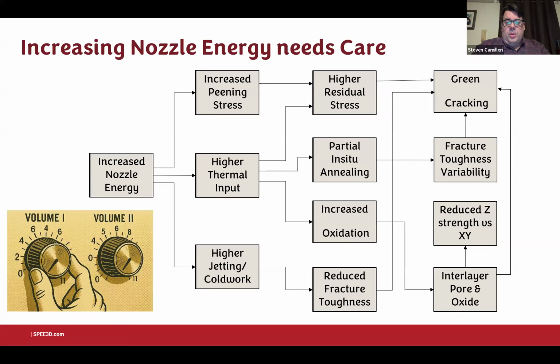Okay, that's level one. What does the increased peening stress actually do though? Well, it's generating residual stress, which may balance against the residual thermal stress, depending on where you're operating. And that's important to consider. The thermal input is, of course, giving you partial in situ annealing, which I think we've just proven was happening in that case. But of course, the higher thermal input is also increasing oxidation.